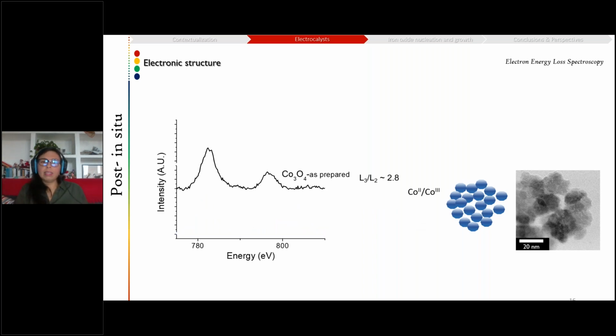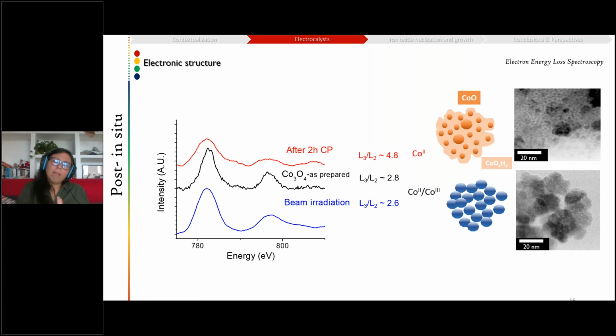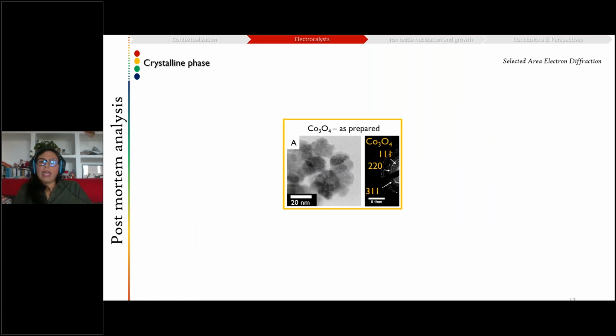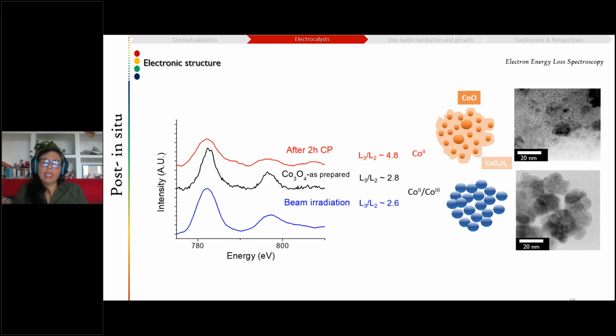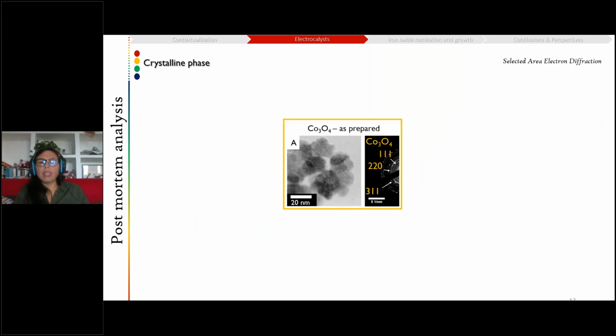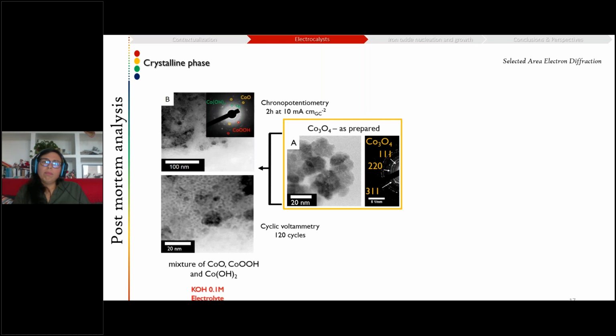Then if we test what happens after 2 hours of chronopotentiometry, we see there is a big change of the ratio of cobalt 2 to cobalt 3, inducing a reduction of most of the cobalt 3 to cobalt 2, forming probably cobalt oxide, which might be the small particles, but also cobalt hydroxide, cobalt hydroxyoxide, that is present in the amorphous way. And this tells us that these transformations are induced because of the electrochemical activity and not because of the beam irradiation.